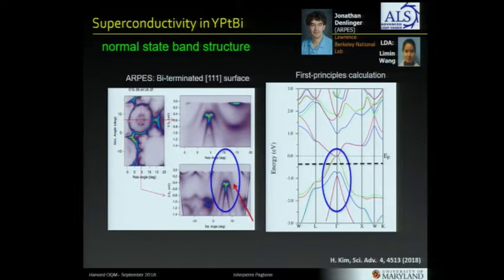So here's some photoemission data, and this is actually still ongoing, but this is some of the data that's in the paper, showing that the bulk band structure actually looks indeed very much like the calculated band structure. Now there's some band bending that we think we understand due to some surface potential, because these are photoemission studies done on these bismuth-terminated states that should give some kind of potential shift at the surface that explains why it'd be different, but it matches down here. And then of course, if your eye is good, you see all these crossing points at 0, which would indicate some kind of states at the chemical potential, and we believe those are, I should say, trivial surface states due to the bismuth termination. But that's part of the ongoing work.